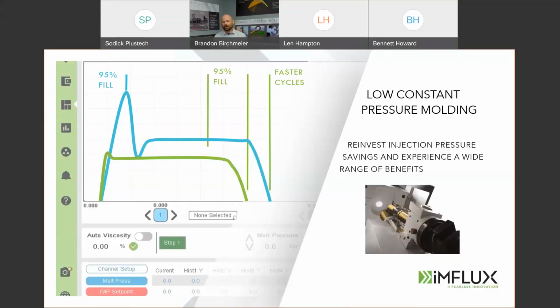that. Overall, we do fill your parts slower. You can see where your 90% fill is in your traditional conventional molding process, right? You're transferring at that 90-95% full stage. With the iMFLUX process, that happens much later on in our filling process. However, we do not require a pack and hold stage after filling. So we actually get some faster cycle time savings here, because if you look at it from an inject forward standpoint, we fill slower typically, but we don't need all the pack and hold pressure to compensate for all the filling we did on the front part of the process.